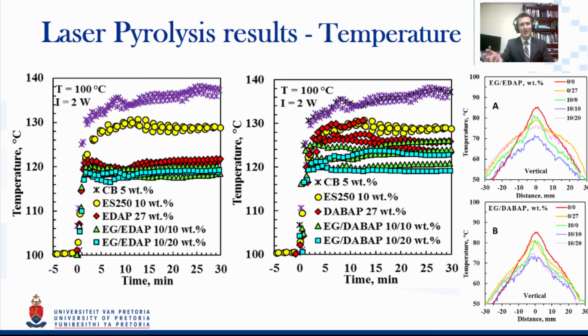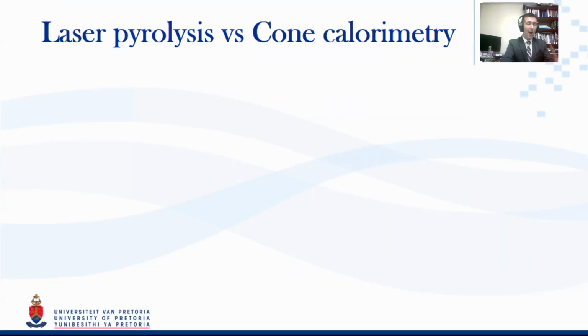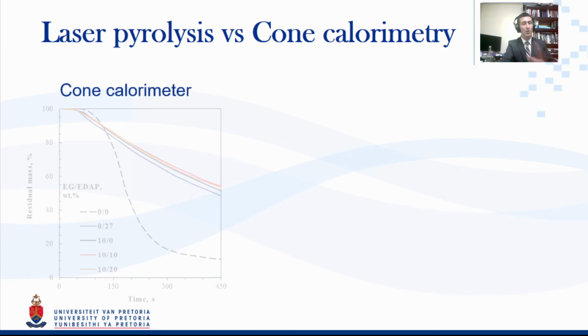And this actually indicated, strangely enough, that the best temperature resistance was actually achieved in the 1010, which is actually our cheapest binary compound, which is a very, very good result. We were quite happy with that. Now we'll get to that comparison. Now, how does this weigh up against cone calorimetry?